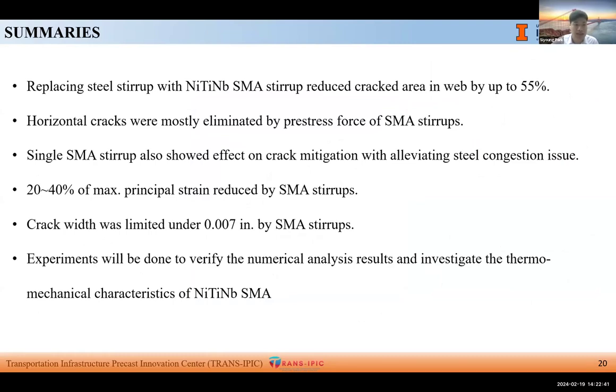To summarize, replacing steel stirrups with nickel titanium niobium SMA stirrup reduced crack area in web by up to 55%. Horizontal cracks were mostly eliminated by pre-stress force of SMA stirrups. Single SMA stirrup also showed effect on crack mitigation while alleviating steel congestion issues. 20 to 40% of maximum principal strain was reduced by SMA stirrups. Crack width was limited under 0.007 inches by SMA stirrups, and experiments will be done to verify the numerical analysis results and investigate the thermomechanical characteristics of nickel titanium niobium SMA.